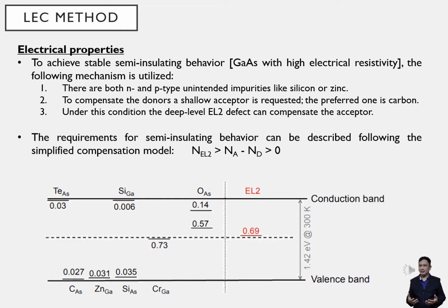The preferred one is carbon. Third, under this condition, the deep level EL2 defect can compensate the acceptor. The requirements for semi-insulating behavior can be described following the simplified compensation model. EL2 is greater than acceptor minus donor, so it must be greater than 0. In this explanation, we can see the importance of the mid-gap double donor EL2 and the carbon. And again, LEC method has a good control of this.